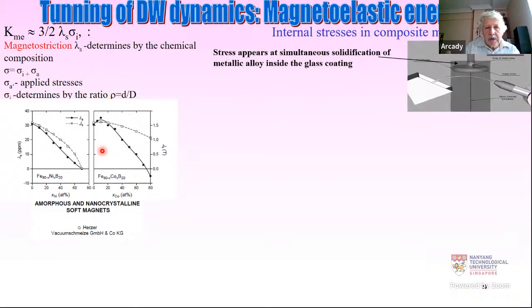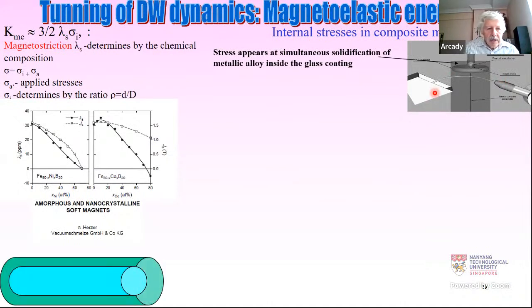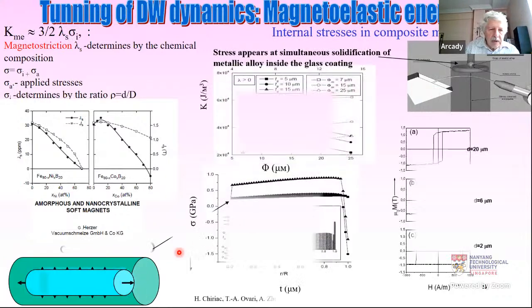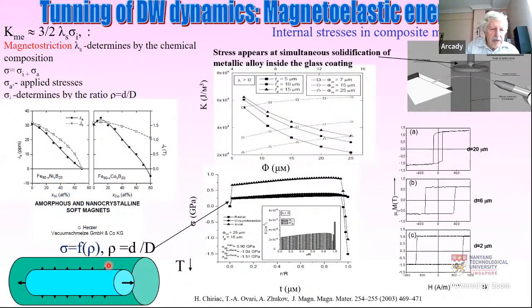But also important are internal stresses, especially in our case, because we have simultaneous solidification of the metallic nucleus surrounded by glass coating during the rapid quenching, shown in this picture. And the important issue is that the thermal expansion coefficients of glass and metal are different. Then if you cool both materials very fast together, you have shrinkage of both materials, but they shrink in a different way.